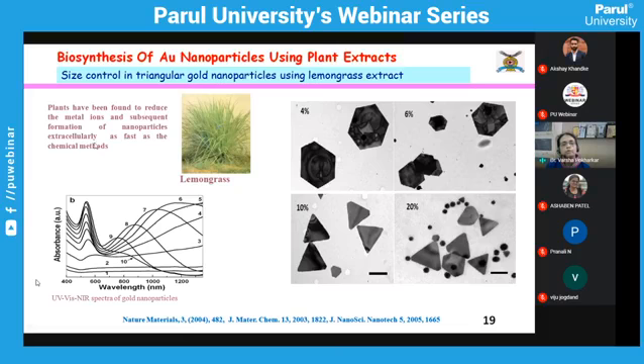And here in this paper, they have cited the use of lemongrass for the preparation of gold nanoparticles, because plant extracts have been found to reduce the metal ions and subsequent formation of the nanoparticles, which occurs extracellularly, and this way very easily we can obtain the gold nanoparticles.